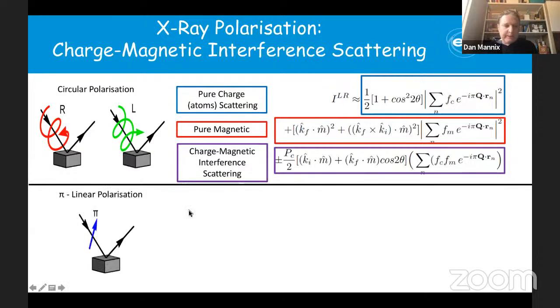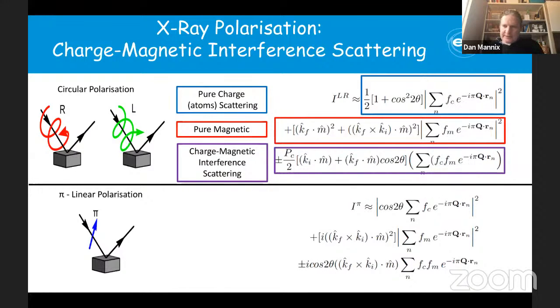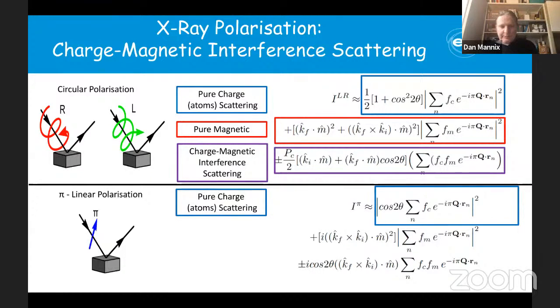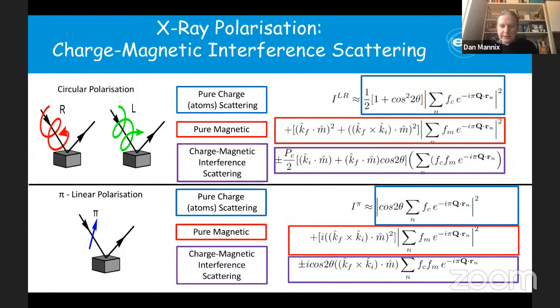There's a similar effect, actually. If you come in with linear pi light, you can get a similar effect. If I write out the intensity that's expected for pi polarized light, we have a first term, which is pure charge scattering, a second term, which is pure magnetic scattering, and the third term is the charge magnetic interference term. This is again related to the total number of electrons multiplied by the strength related to the resonance that you are looking at. It also has a polarization factor that depends on the direction of the magnetic moment. So this is where you can get magnetic information as well from this resonant term. Both of these terms give you magnetic information. Now, the pi light is one that has an electric polarization in the scattering plane. Sigma light, which is the one that usually comes out of a synchrotron, doesn't possess a resonant and interference term, so you can't really use the sigma light to do this trick of getting charge and magnetic information.